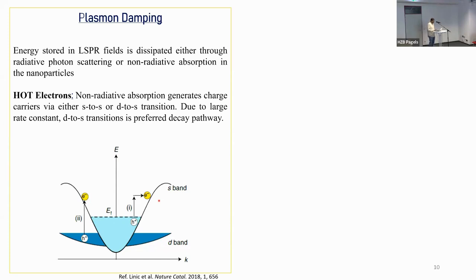However, the challenge is that the lifetime of these electrons is extremely short, right? So before they can be injected into something, they will try to recombine. The lifetime is less than 10 femtoseconds. So that is the challenge.